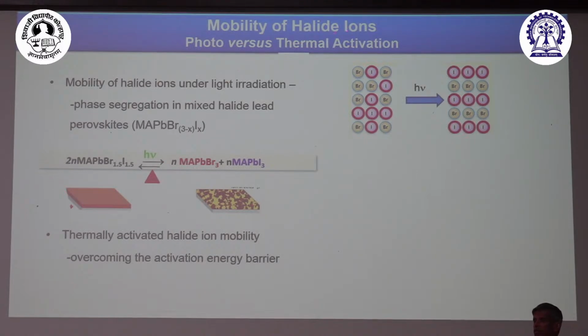So this drew our curiosity when we first saw the paper from McGehee's group, and we said, okay, what is causing it? We published more than half a dozen papers, each a step in the finding. First, we wanted to see what the kinetics of it is. Then we wanted to see what factors control this kind of movement. What happens, whether it comes out in solution. So those kinds of things we studied, and we finally said that it's the hole extraction by iodide that causes this change, because once the holes form iodine, it starts moving away from the lattice, and even comes out into solution, if you have it in contact.